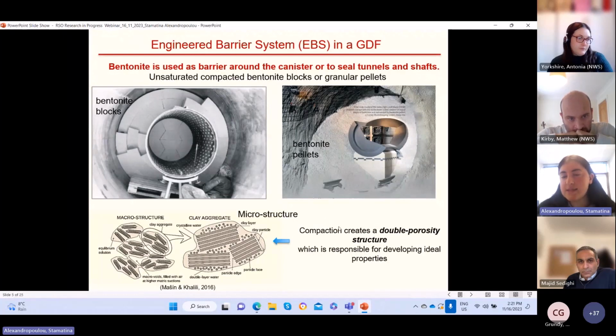The challenge here is that the compaction creates a double porosity structure, which is responsible for developing ideal properties. And because it is a clay, if we are using a microscope, this is the formation that we can see. So as we can see here, we have clay aggregates, and between them we have some voids, which consist of macrostructure or macroporosity. Whereas each aggregate has clay particles, and there is also porosity in each aggregate itself, which is called microstructure or microporosity.